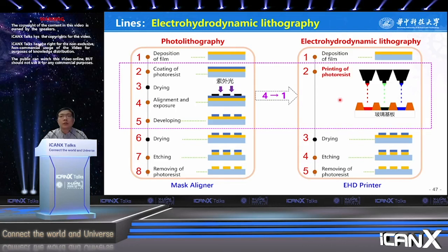EHD lithography is a short flow process and can reduce 3 steps. Finally, the resolution of EHD lithography is high enough. It can reach about 100 nanometer, much higher than the conventional mask aligner in a university lab, whose resolution is about 1 micrometer.